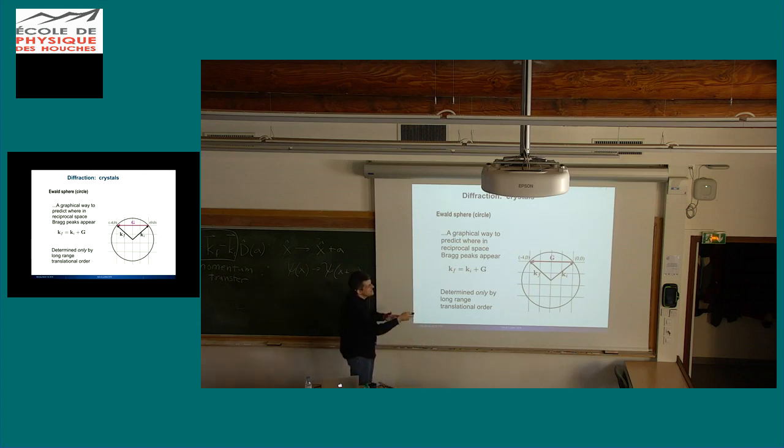But that's the basic idea that you can look at certain cuts of this 3-dimensional reciprocal space, but for one given measurement, you're actually making a lower dimensional cut through the surface than the full 3 dimensions. So in this case, this is a 2-dimensional crystal. You'll notice that the cut that I make is 1-dimensional. If I had a 3-dimensional crystal, I'd still only be able to make a 2-dimensional cut. And in order to get a full mapping of reciprocal space, you need to do a bunch of measurements where you change either the wavelength or the orientation of the crystal.